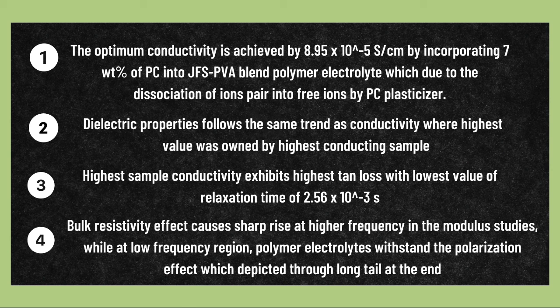Move on to the conclusion part. You can see the optimum conductivity is achieved at 7% of PC. And then the dielectric properties also follow the same trend as conductivity, where the highest value is owned by the highest conducting sample. Next, the highest sample conductivity exhibits higher tangent loss with the lowest value of relaxation time.